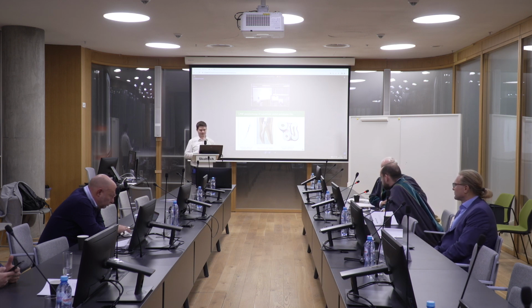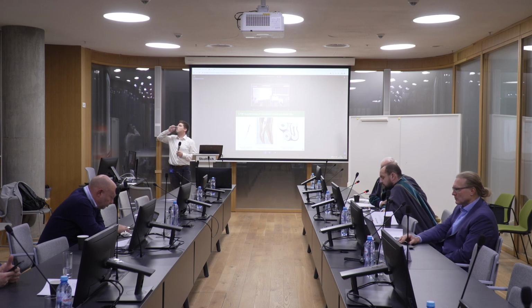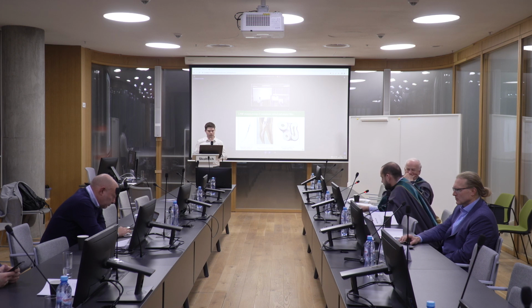Yes, thank you for the interesting talk. I have a few questions. One question: it's not clear how the grain size and grain orientation influence the mechanical properties of the printed materials, because mainly you study only one orientation, vertically oriented samples. But it's also interesting to study what will happen if you change the grain size and print the sample in another direction. This is the first question. And maybe I continue and give some remarks about the second one. From the experimental part of the work, it's clear to me, it's really good results, but the theoretical part is not clear to me, because if we look at the vapor pressure for nickel and titanium, we easily realize that, of course, nickel will evaporate earlier. So why did you decide to conduct this study? Because you can estimate this effect by analyzing the vapor pressure at different temperatures.